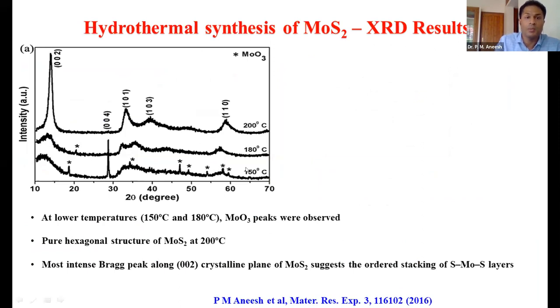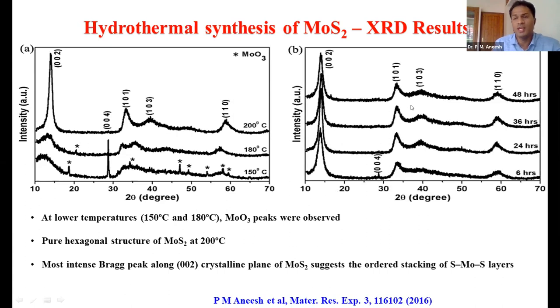This is the X-ray diffraction spectrum. You can see the star marks that represent some impurity peaks corresponding to molybdenum oxide. At 150 degrees and 180 degrees, you can see there are some impurities, but 200 degrees corresponds to the perfect MoS2 sample. At low temperatures the sample contains MoO3 peaks, but at high temperatures it contains MoS2. Another thing, we varied the time as well to study the dependence on the duration of the annealing.